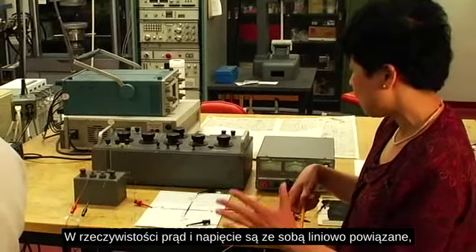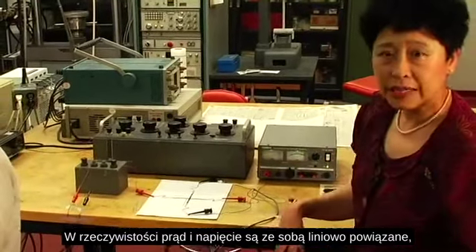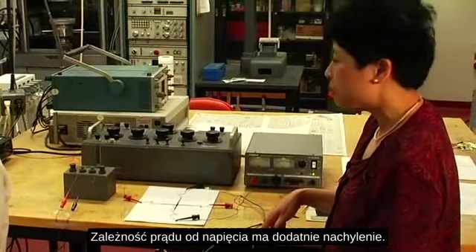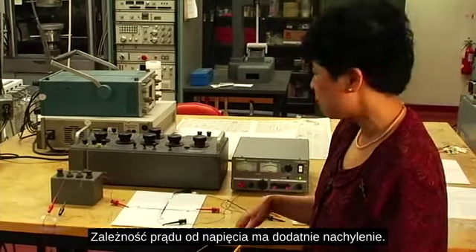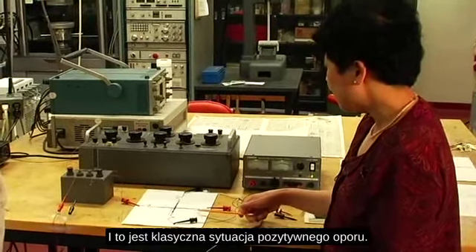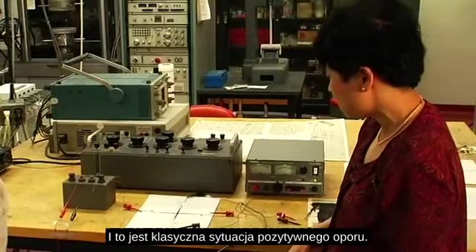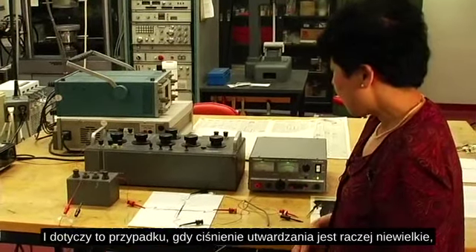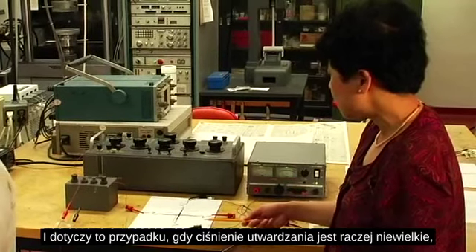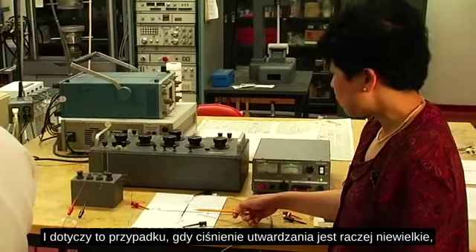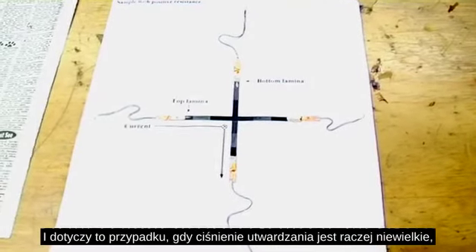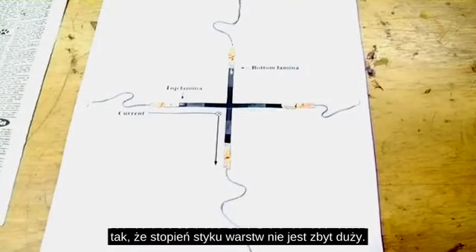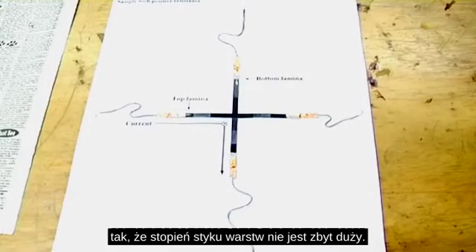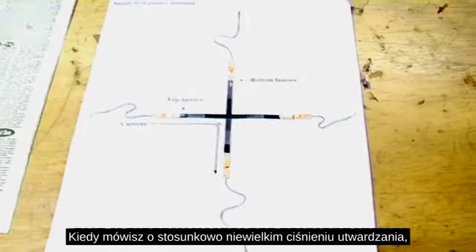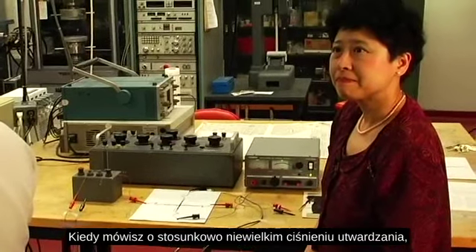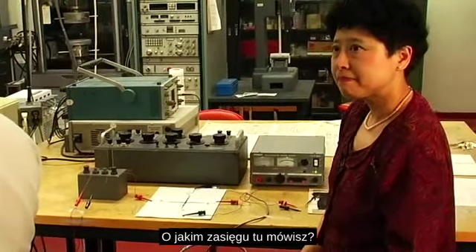In fact, the current and voltage are linearly related to one another, with a positive slope. The current-voltage relationship is positive in slope, and this is the classical positive resistance situation. This applies for the case of the curing pressure being rather small, so that the extent of touching across the layers is not very high. When you talk of the curing pressure being comparatively small, what range are you talking about here?